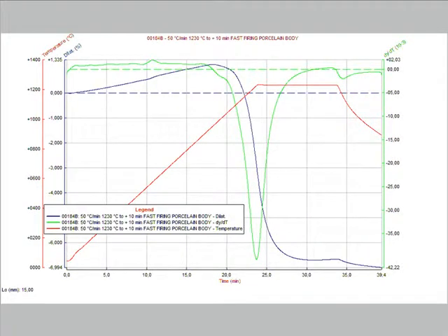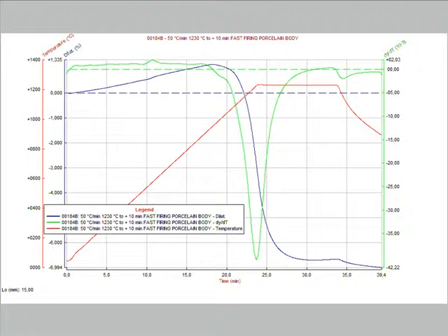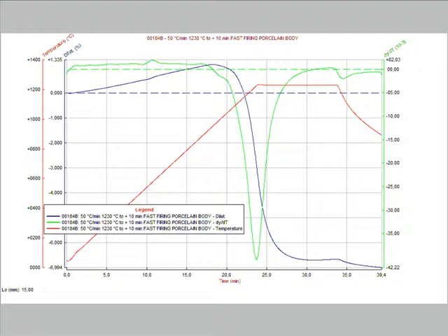Now, carrying out a second test with the same heating rate up to the temperature of maximum sintering speed, followed by a permanence at that constant temperature, it is possible to know how much time is necessary to hold the temperature in order to reduce the sintering speed to zero. Managing in this way it is possible to design a heat treatment with the optimal temperature and the minimal holding time for the sintering process.